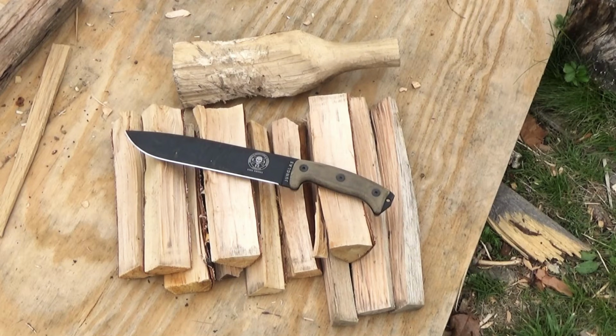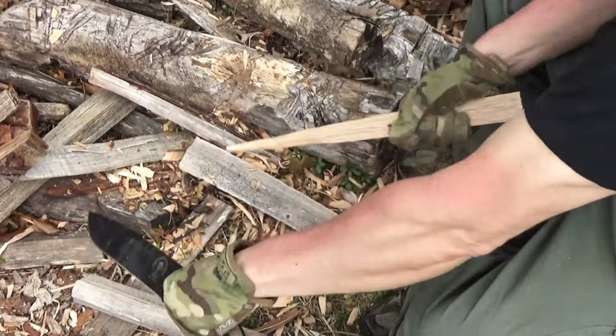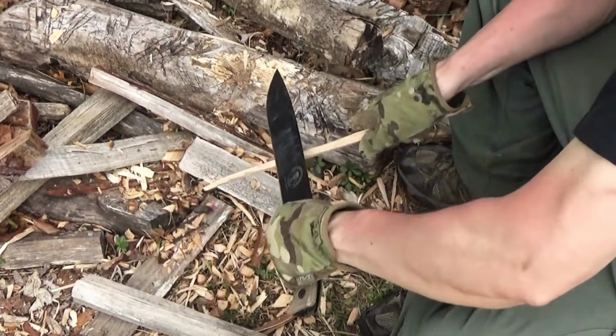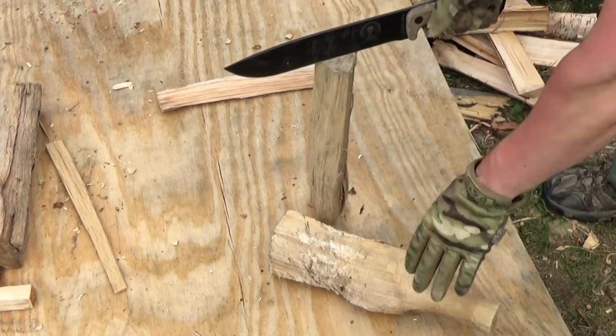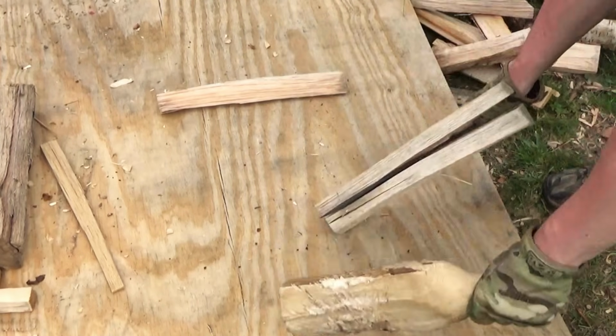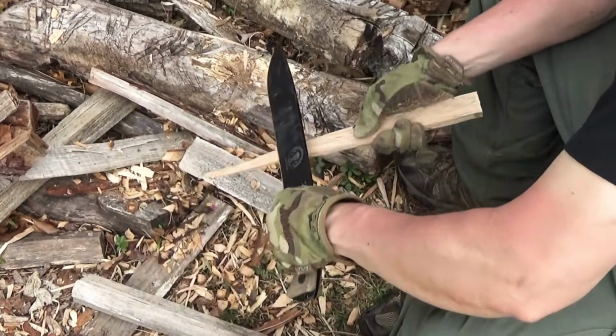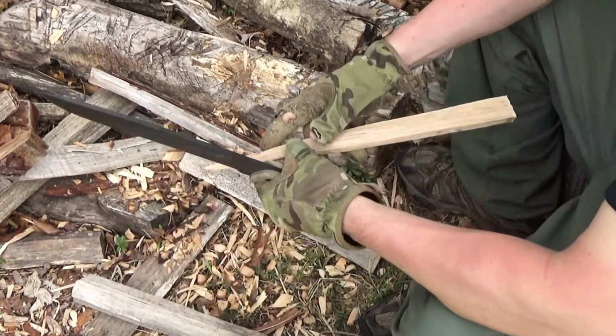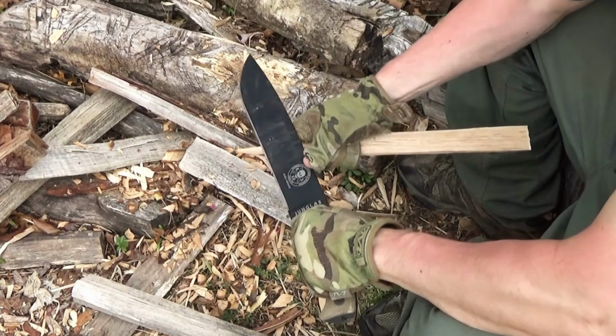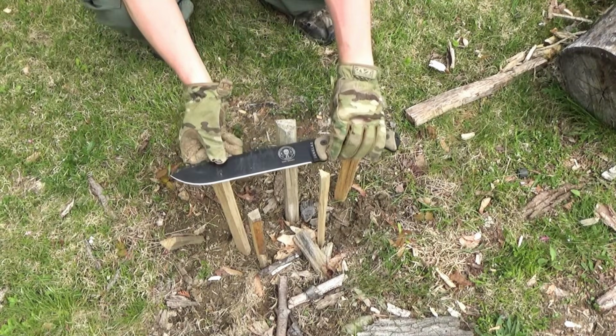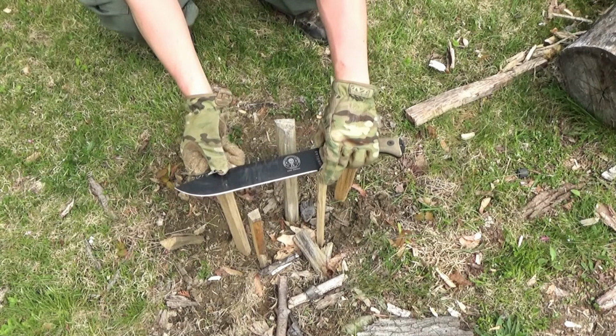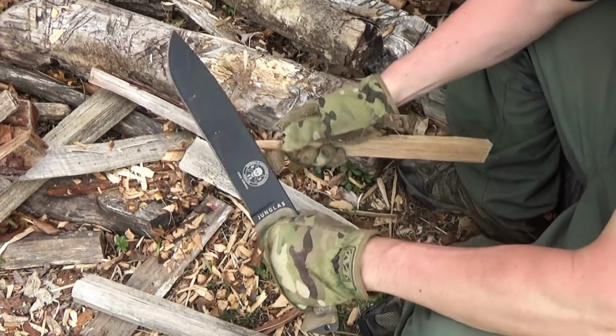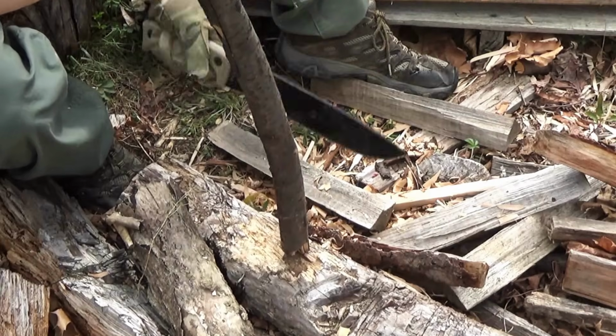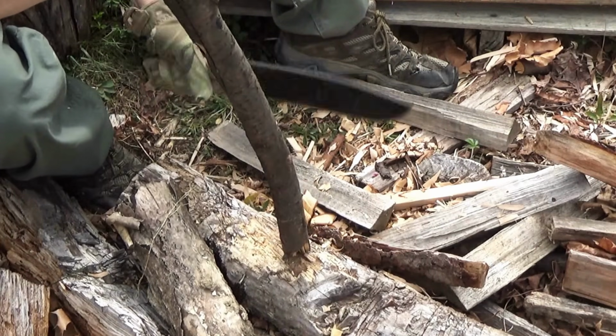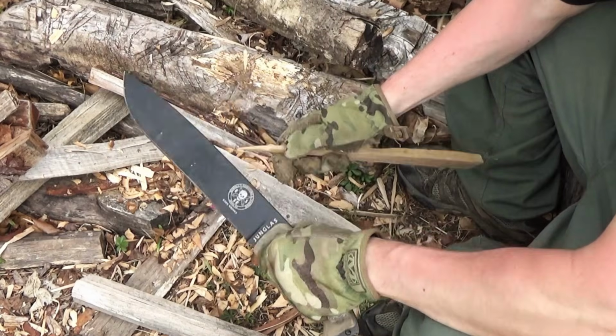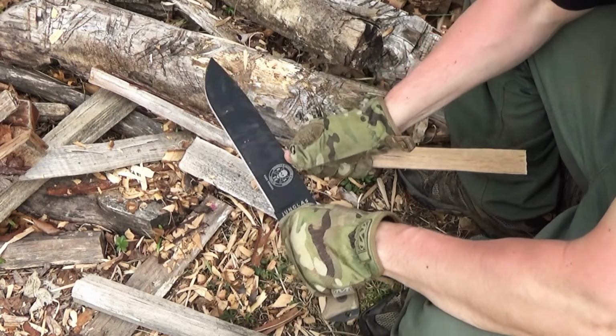In the destruction test, the original Junglas passed all 6 categories. Battening, 45 minutes on the hardest material in this test, 0 edge chipping, 1 minute of rolling that field sharpened in 4 minutes. Nail chop, 1095's toughness produced edge rolling without chipping, resharpened cleanly. Prying, the wide blade geometry and thick spine distributed lateral force without tip deflection. Lateral stress, flex and return, 0 permanent deformation. Saltwater, 1095 produced surface rust at 12 hours, manageable with maintenance. Pommel hammer, 0 handle movement across 50 strikes.